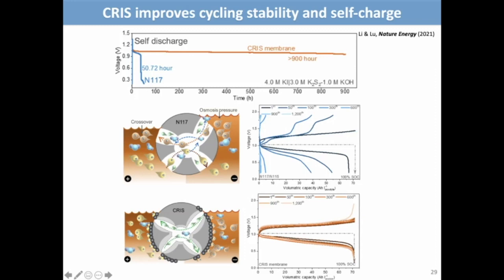And if you do charge-discharge cycling, you can also see that the profile of the cell using this membrane is very consistent over 1200 cycles, but the one with just Nafion starts to decay even at the 50th cycle.